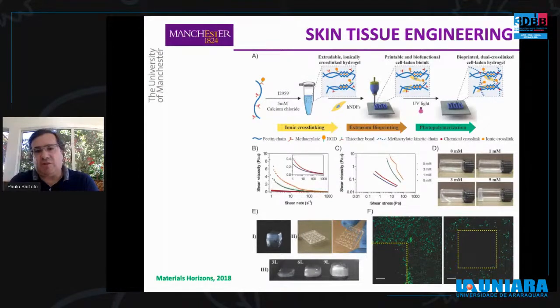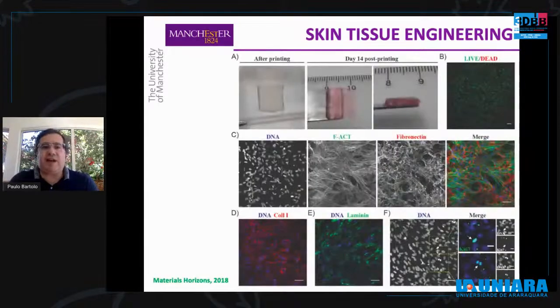The amount of calcium chloride was investigated and optimized regarding the flow properties of our material. And we explore also different types of photoinitiators, and the amount of photoinitiator was also optimized regarding the curing kinetics and also the biomechanical properties of the final gel. Preliminary results show that after 14 days post-printing, cells were alive, creating cell networks, and also able to produce their own extracellular matrix.